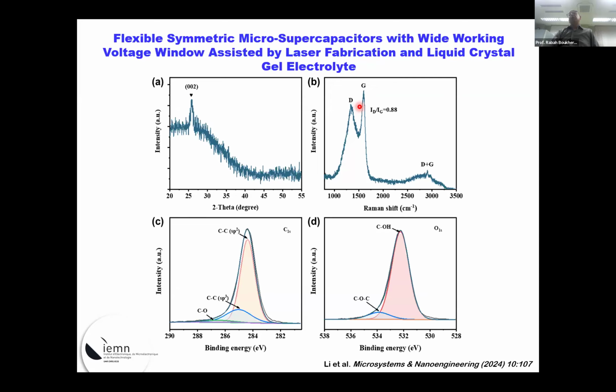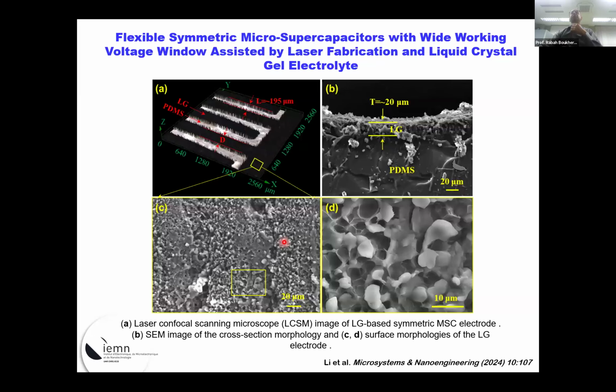because the way you make the laser-induced graphene, indeed, it's defective because you use a high power and high energy. So it's not like CVD graphene or carbon nanotubes, where you have almost no defects. Here, indeed, you're mostly dominated by defects, and you have a lot of edges as well, which consist essentially of carbon-oxygen. Because it's done in air as well, you oxidize the surface slightly. You can see it with the XPS, but essentially you have carbon sp2.